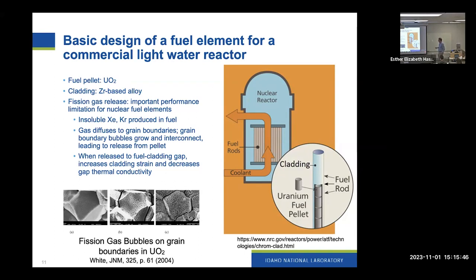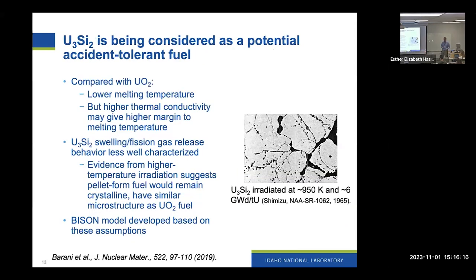Eventually, as those grain boundary bubbles grow and interconnect, they can form a fully connected pathway to a free surface. That leads to release of these gases to the gap between the fuel and the cladding. When that happens, it increases the strain in the cladding, and it also decreases the thermal conductivity of the fuel, which basically raises temperature and puts us closer to an accident type scenario.